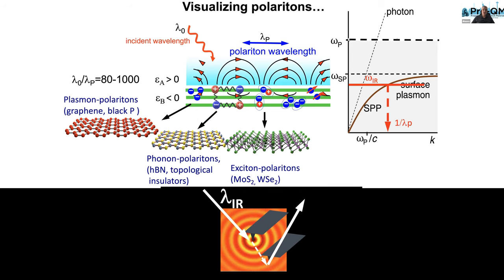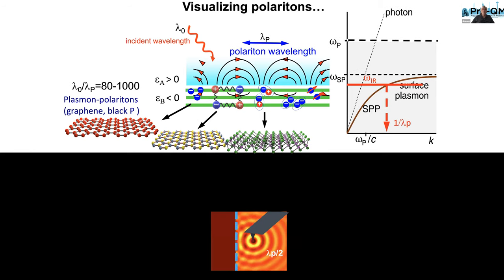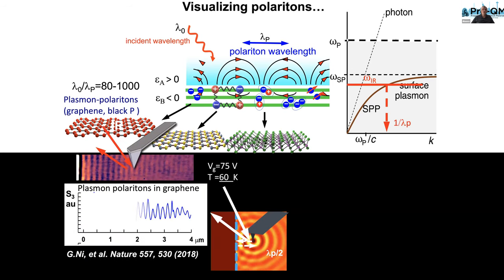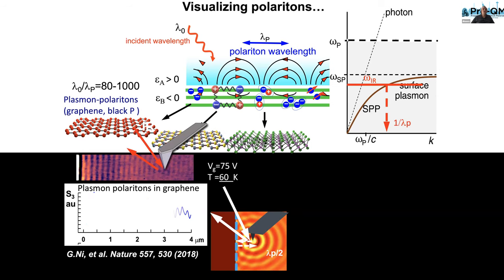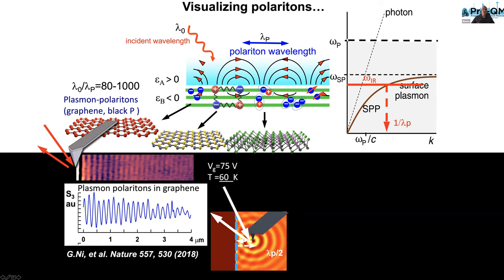This is doable, but this is not very practical. And what we are typically doing instead is the following. We form standing waves between the tip and the physical edge of our crystals. So we launch the wave, we collect the reflected wave, and we send light to the detector. And in the raster scanned image, these polaritonic waves look like oscillations of our near field signal, starting from the interior of the sample, going to the physical edge of the sample. So this is the first time we were able to image these waves at cryogenic temperatures.